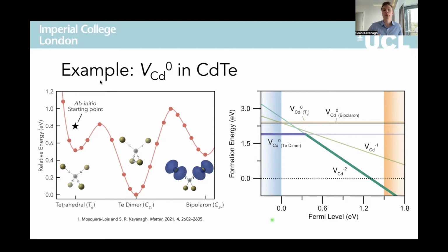Normally, we just show the lowest energy, i.e. the most favorable charge state for each value of the Fermi level, which would correspond to just the saturated color lines here. And this simplifies the analysis and the diagram when considering a broad range of defects at once.